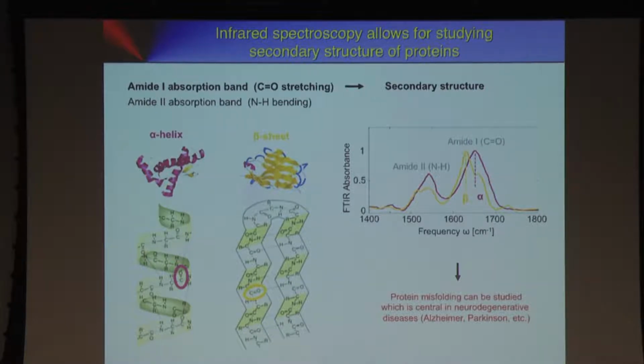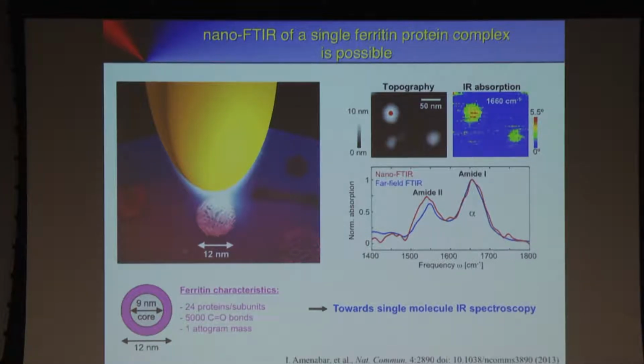So it's really a significant contrast. But up to now, this could only be done on a microscale level. So the question was, can we do that on a single protein level? First, we wanted to look at a small object, but we didn't want to go for a single molecule because we don't yet have single molecular sensitivity. So a colleague recommended ferritin. It's a protein complex, but a single one. It's the particle that stores iron in our body. It has a 9 nanometer ferrihydride core surrounded by a 1.5 nanometer thick protein layer. From X-ray structure, one knows that it consists of 24 protein subunits, corresponding to 5,000 bonds. That's a really small amount, and it's 12 nanometers in diameter, so we can easily identify individual particles by topography imaging.